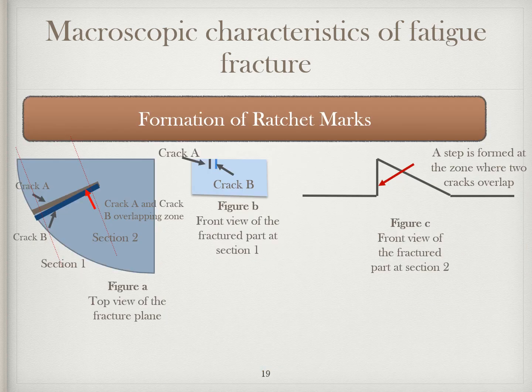Let us now try to understand how the ratchet marks are formed. When several fatigue origins are adjacent to each other, each will start its own fatigue crack propagating. If the origins are roughly in the same plane, the fatigue crack growing from one origin will start to overlap the fatigue crack from another origin. Figure A shows two cracks, crack A and crack B, with different origins. They are originating from the peripheral surface of a circular shaft and they are propagating towards the center. After propagating a certain distance, they overlap each other. So the figure is the top view of the fracture plane.